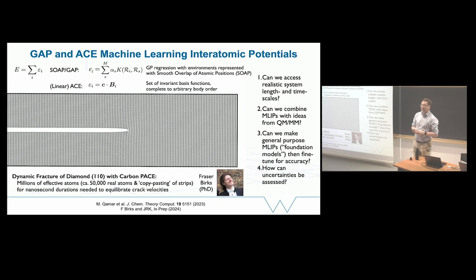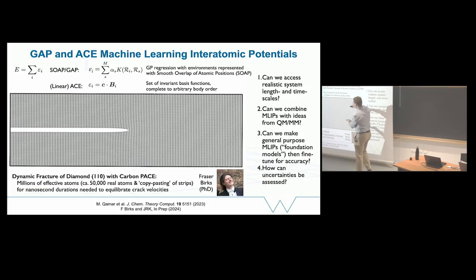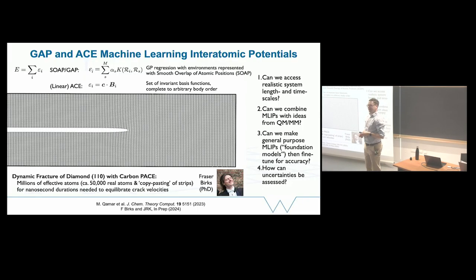You use periodic boundary conditions. Yes. You have some stresses in the whole box, and so it's periodic in the Z direction. It's got open boundaries at the top and at the two sides, so that you can apply the stress. That's right. And applying uniformly in the whole. Yes. This is the so-called thin strip geometry, which has a mathematical solution, so we know in the continuum problem what we would expect, and then we can see how the atomistic solution differs from it.